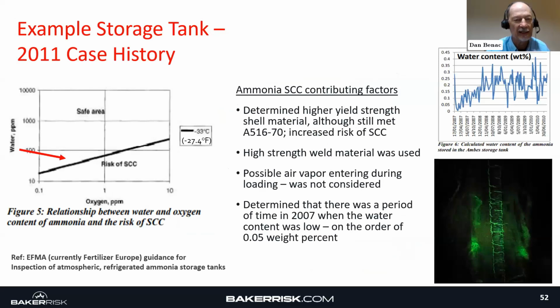As an example of that, this is just an example of how we applied some of the things that we learned about a damage that occurred in a storage tank in 2011, where the reality of the situation is ammonia stress corrosion cracking is a known phenomenon that can occur. And the issues at hand with that are the ppm of oxygen and the amount of water.